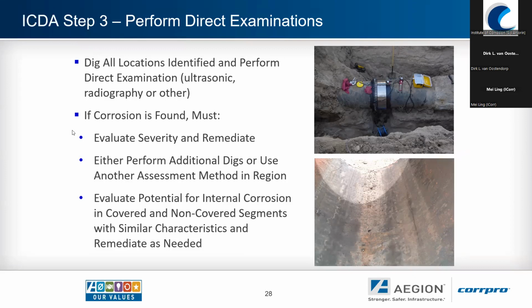According to the regulations, if there is any corrosion identified, it's important to evaluate the overall severity of the corrosion at that location and identify potential remediation methods. If there are any discrepancies, it may be necessary to conduct additional digs. And this is where it gets a bit awkward, because you're also required to evaluate the potential for internal corrosion, even if it's not in these high consequence areas. But if there's a severe location that wouldn't be from a public standpoint, they will also require further investigation.